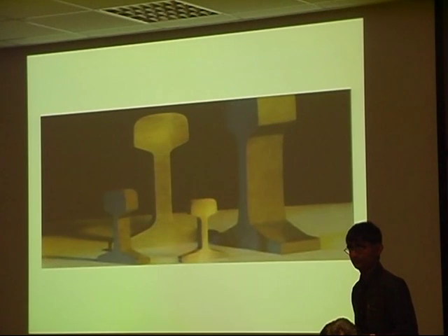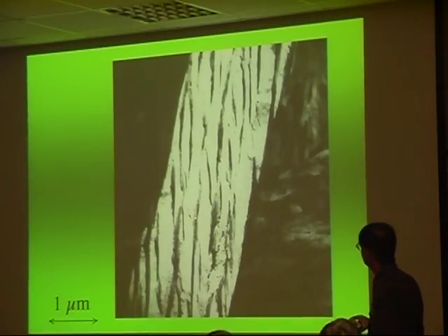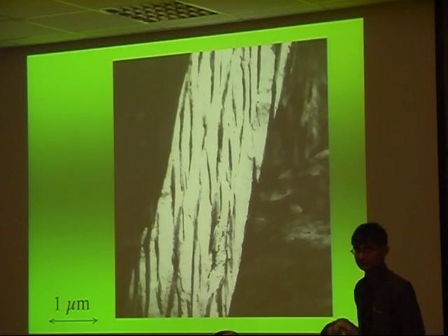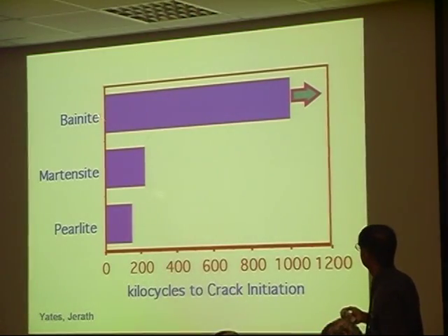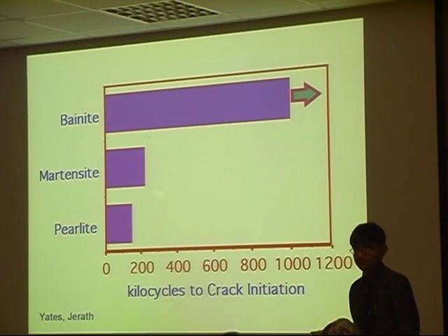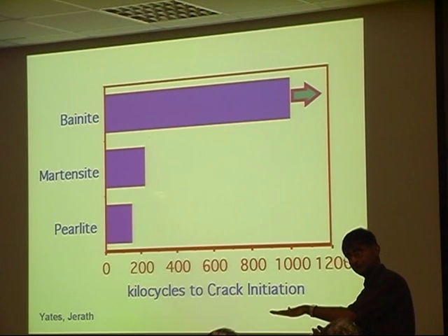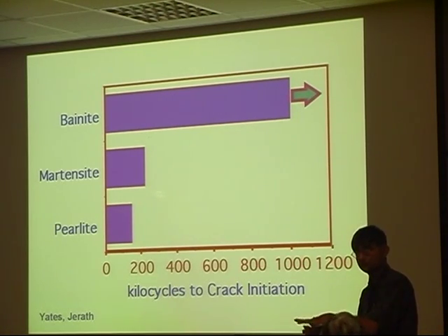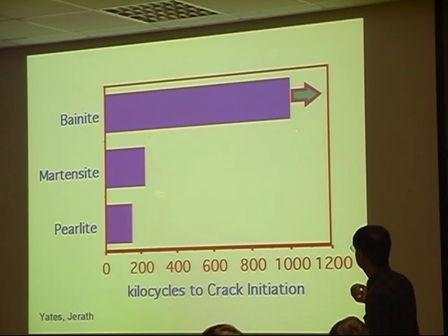These rails are produced with a completely different microstructure. They have no cementite. They are basically plates of bainitic ferrite and retained austenite. And they have remarkable rolling contact fatigue resistance. So this is, every time a wheel goes on top of a rail, it induces a stress under the surface. And that causes fatigue. And it peels off.